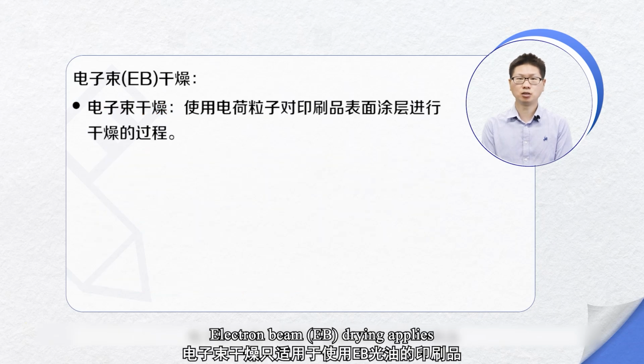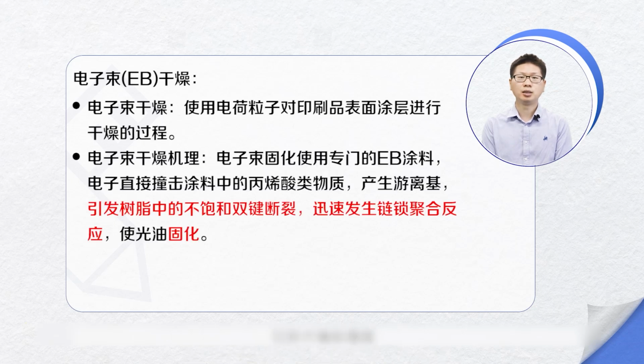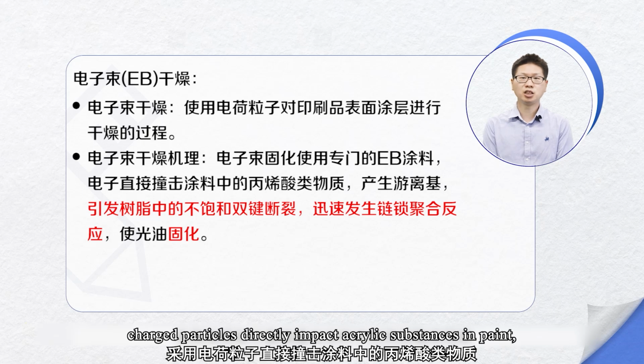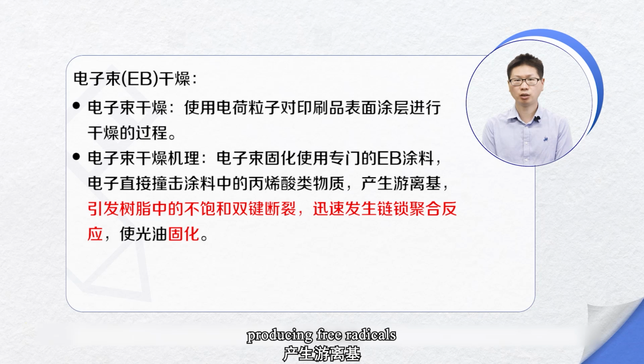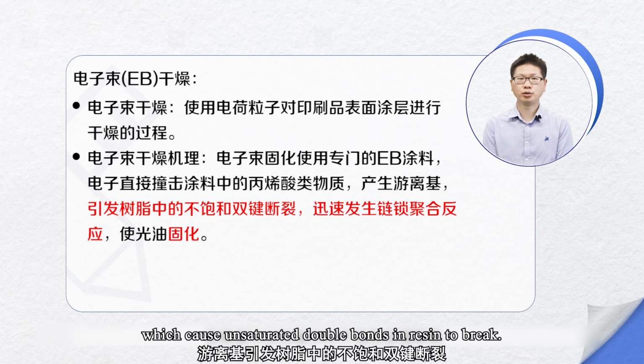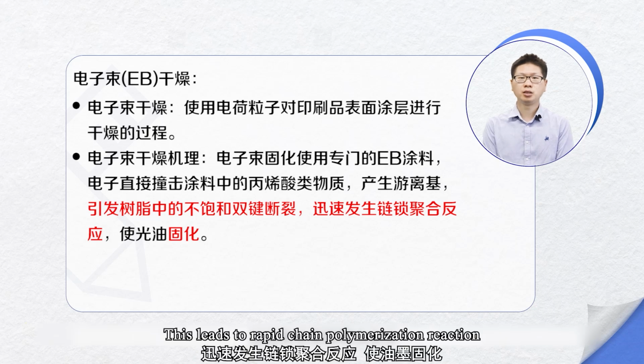Electron beam (EB) drying applies only to printed materials using EB varnish. In this method, charged particles directly impact acrylic substances in the paint, producing free radicals, which cause unsaturated double bonds in the resin to break. This leads to a rapid chain polymerization reaction, resulting in ink curing.